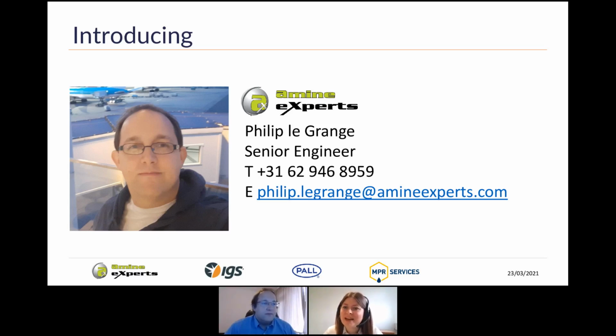Question from Abdurrahman. In an FCC unit, what is the best product to use, MEA or MDEA? It would depend on what pressure you're operating at. There are a lot of considerations that go into what amine to use. Generally, MEA is quite old-fashioned, so we wouldn't build a new plant with MEA, generally speaking. But one of the challenges of switching away from MEA to MDEA is that MEA is a very strong base and can treat at very low pressures. So if you have a low pressure fuel gas absorber and need to meet a tight specification, it can be a challenge to switch from MEA to MDEA, even though there are usually some corrosion advantages and other advantages in doing so. So it's something the case needs to be looked into in a little bit more detail. Thank you, Philip.